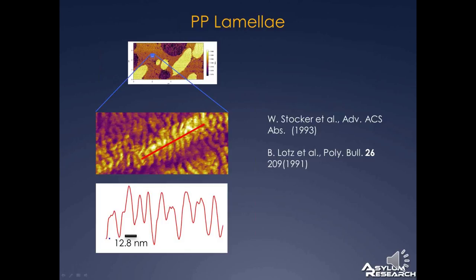Okay, this is a question about sample roughness. You've mentioned the effects associated with the difficulties of controlling the contact area due to the tip shape, but the sample is also important. The examples you've shown have topographical features quite clearly. Isn't that affecting the ultimate calculated stiffness? Definitely. That's one of the reasons, with a lot of the stuff going around with force curves right now, fast force curves, with these kinds of measurements, you have to take into account that contact area, and the sample roughness will change that contact area, and therefore, if you use the simple stiffness measurement you make to make a modulus measurement, you'll get the number wrong. So that's why we try to be very careful about that, and we try to do it on samples that are as smooth as possible if we want that to be a quantitative value.